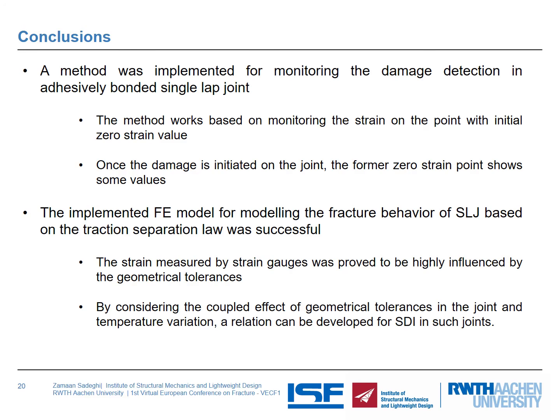As for the conclusions, a method was implemented for monitoring damage detection in adhesively bonded single lap joints in this work. The method works based on monitoring the strain at the point with initial zero strain value. Once the damage is initiated on the joint, the former zero strain point shows some values. The FE model implemented for modeling the fracture behavior of the single lap joint based on the traction separation law was successful. The strain measured by strain gauges was proved to be highly influenced by the geometrical tolerances. By considering the coupled effect of geometrical tolerances in the joint and temperature variation, a relation can be developed for the structural damage indicator in such joints.